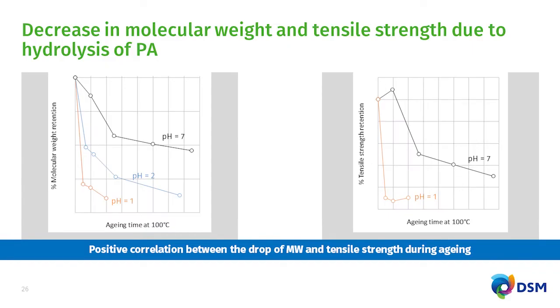Now, the next few slides highlight the impact of hydrolysis on polyamide properties. The left-hand side figure shows the molecular weight retention of polyamide after aging at 100 degrees Celsius at different pH levels: pH 7, pH 2, pH 1. You can think of pH 1 as a condition familiar from exhaust gas recirculation tests. The EGR test is typically pretty acidic, and if you put a polyamide that is not resistant towards acid-catalyzed hydrolysis, you will have pretty fast degradation. This indicates that acid plays a role in degradation. The lower the pH, the more the acid, the faster the molecular weight of the polyamide goes down.